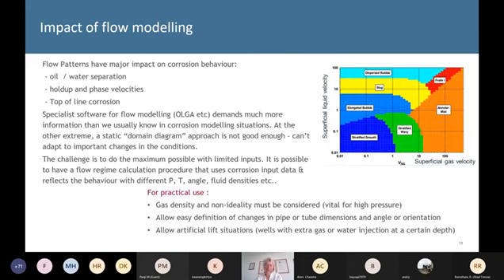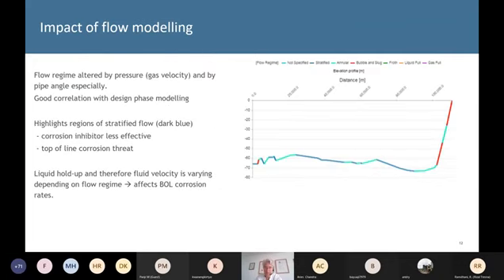What we feel is that you need to take into account that you don't have ideal behaviour in gases. That's one important thing, particularly at very high pressures. We definitely need to take into account the tubing deviation or pipeline elevation, because the angle of flow of fluids is important. And in wells, we have the injection of gas at certain depths or the injection of water in some kinds of secondary recovery, and those need to be considered. So all of these things need to be considered in the modelling, which make it a practical model, and these are not readily incorporated within simple flow modelling systems.